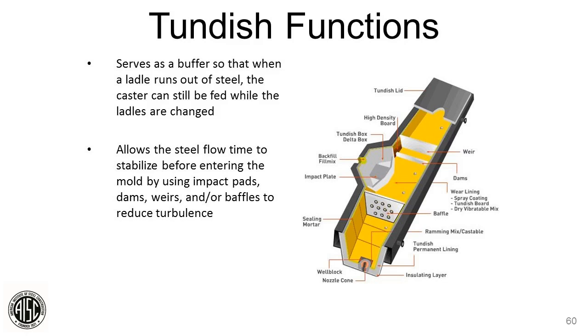Here's the Tundish, kind of an overview schematic of the Tundish. It's a buffer. So we're continuously casting, so something has to be a little bit of a reservoir there while we're swinging the other ladle into the casting position. So this will hold 15, 30 tons, depending on the size of the Tundish. And just a real quick overview, but you look at it, it's got dams and weirs, impact pads, so as liquid steel comes in, it's distributed uniformly. So the goal here is each strand gets steel at the same temperature and the same chemistry. You don't want a short circuit event where 2 strands are hotter than the 2 outside strands. You want the steel temperature consistent across all the strands as it goes into the molds, so we have a quality product. And go to the next slide, please.